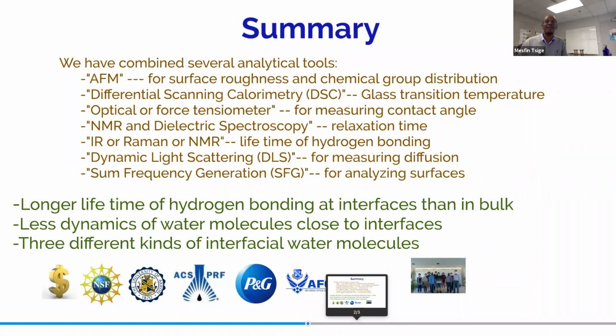Yeah, that's a very good question. Exactly. In our case, even the question at the beginning in the classical simulation community was, is it really appropriate to say that hydrogen bonding can be actually captured in a classical sense? Then the answer for that was yes, because 95% of this hydrogen bonding is electrostatic. Only maybe 5% is covalent bonding, which means in our classical simulation, we can capture that 95% of hydrogen bonding through partial charges. So we have the oxygen of the water molecules negatively charged and the hydrogen atoms positively charged. As a result, they form dipoles. So that dipole is correctly captured from the classical simulation of water.